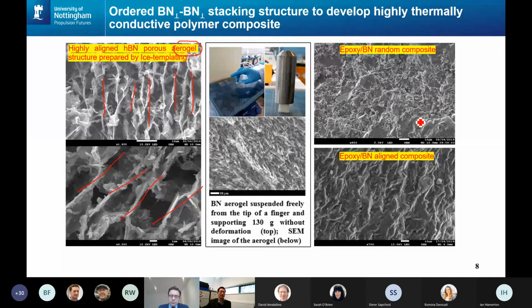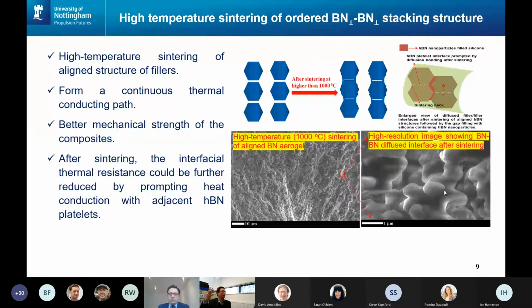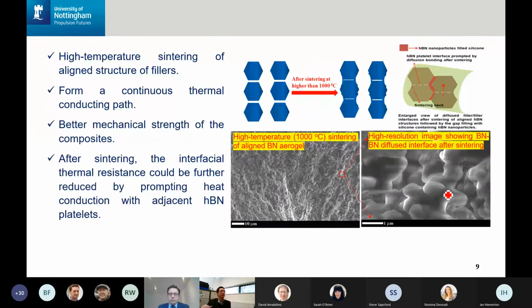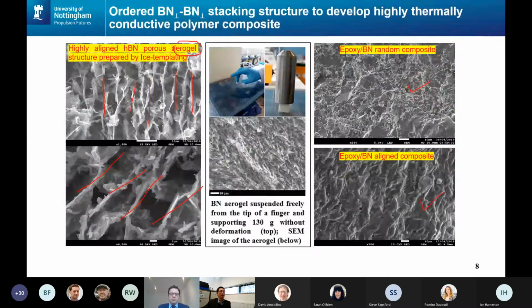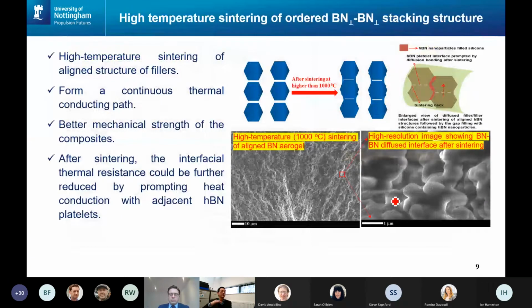After that, one way is we can directly do the impregnation of polymer, for example epoxy. As you can see here, this is a randomly distributed skeleton plus epoxy, and this is aligned boron nitride plus epoxy. But this one is just a physical contact. So we can think about whether we can make it more solid.